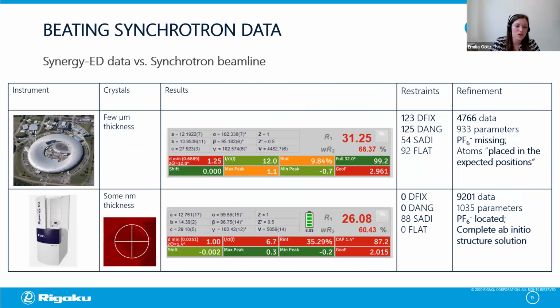And interestingly, they also tried the structure solution at a synchrotron, and the electron diffraction data led to better results. So you can see that the structure from the synchrotron data was only achieved by using loads of restraints, and even then the PF6- was missing and atoms were basically placed in the expected positions. For electron diffraction data, the structure solution could be performed ab initio, and the PF6- was located. There was barely any help from restraints or constraints. And even though electron diffraction is not famous for its low R values, in this case, the R value was actually lower than the one from synchrotron data.